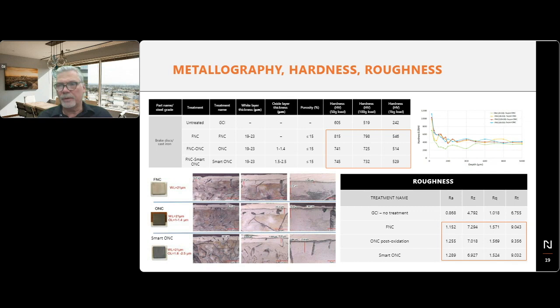So there is a sweet spot probably for roughness, and it just shows that we try to limit, and we can limit in the process, increase of roughness, but it always still depends on starting roughness. In manufacturing operations, depending on tooling, if it's brand new or a bit older, a bit more worn out or less, you may have different types of roughness within similar batches from one day to the next. Therefore, it is very difficult to keep track.